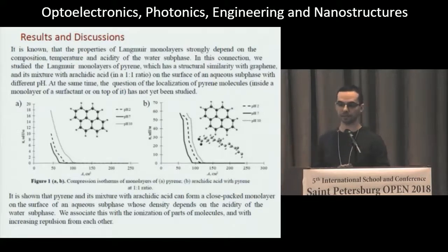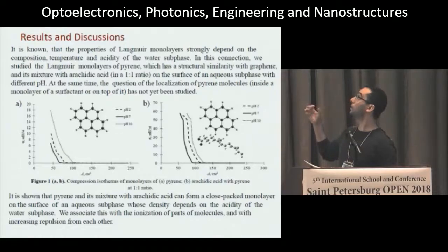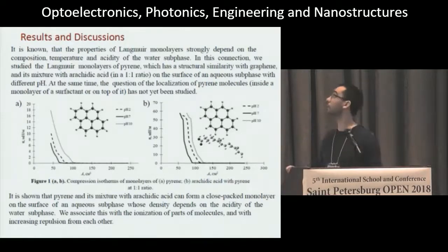The monolayer has no stability over time. So, in the figure, we have a composition of pyrene with arachidic acid. This arachidic acid will support the monolayer and will increase the stability over time.